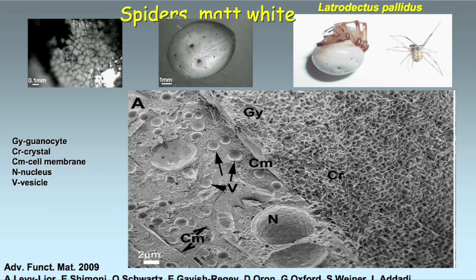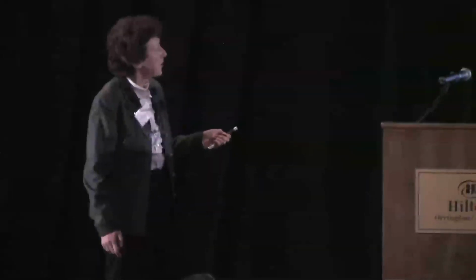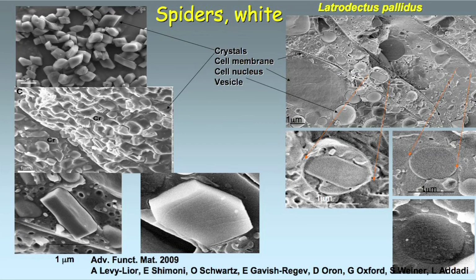And finally, let's take a look at the matte white spiders. You can see here these sacs of cells, of iridophores. And when we look into the iridophores, we see that there are cells that are completely chock full with crystals. And the crystals are not ordered, and they don't look like thin plates. In fact, when we isolate them, they are prismatic crystals. And in the cytoplasm, we can even see crystals embedded with very nice shapes. But there are also vesicles. And the vesicles are full of a material that is not etchable, so it is probably also amorphous guanine. And in some cases, we can see a crystal formed in the vesicle from the amorphous material.